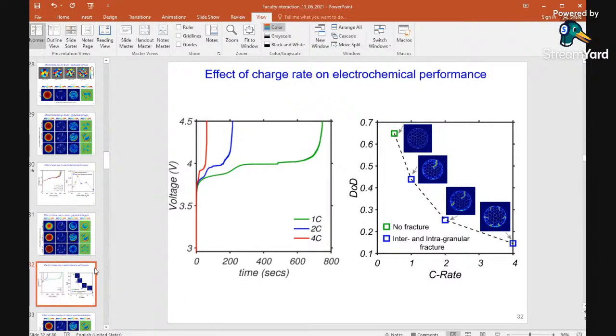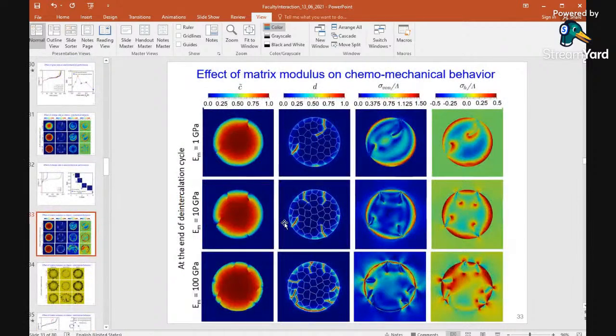Now the next part we would like to focus on is the modulus, that is, how the surrounding material is contributing to the fracture process. So we consider a matrix with different Young's moduli, starting from 1 to 100, so that we consider polymer-based electrolyte up to any solid electrolyte, which is almost 100 GPa, and we investigate that with a particular grain size.